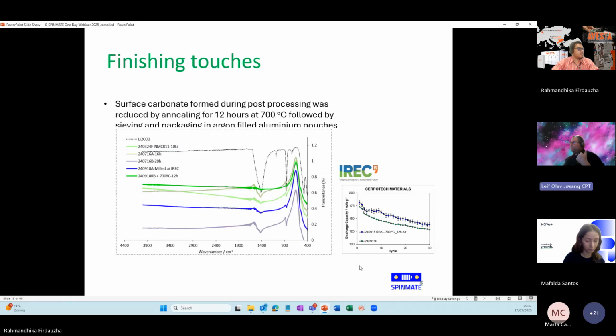So we produced by spray pyrolysis, followed by calcination, milling, sieving, remilling to improve yield, sieving again, and an annealing process. Calcination at 850 and annealing at 700. Then we packaged in aluminium pouches, which we filled with argon alongside the powder.